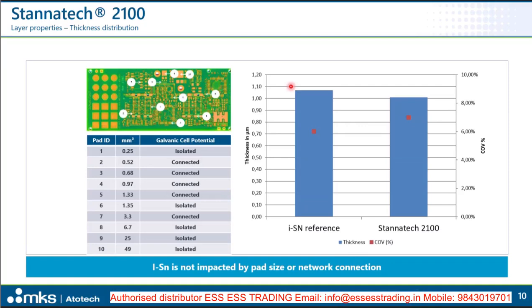Let's look at the layer properties, starting with the thickness distribution. What you see here is a comparison of a reference process with the Stannatech 2100, and we look at the thickness distribution depending on pad sizes. This was measured on a test substrate with different pad sizes, with connected and isolated pads, in a pad size range of 0.2 square millimeter up to 49 square millimeter. What you see on the right is that the target thickness is pretty similar, and the thickness distribution is also in a similar range for both.